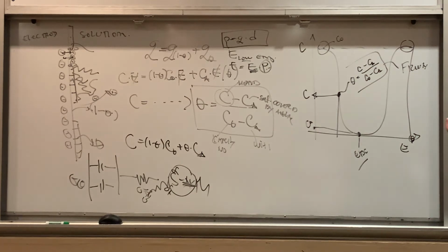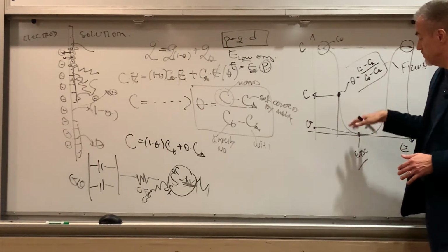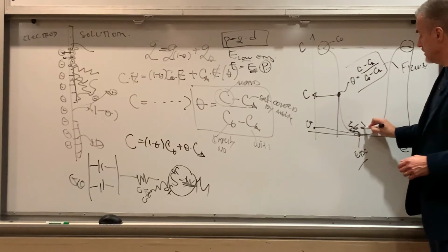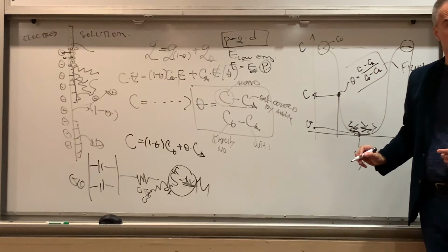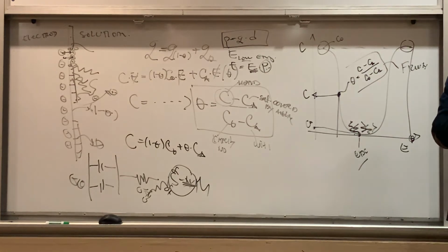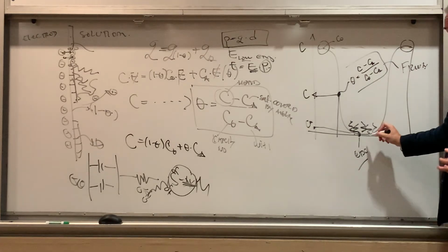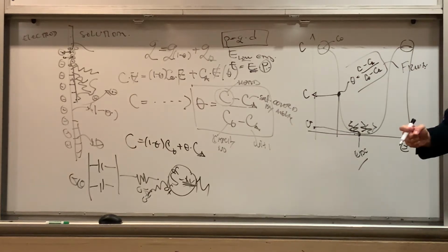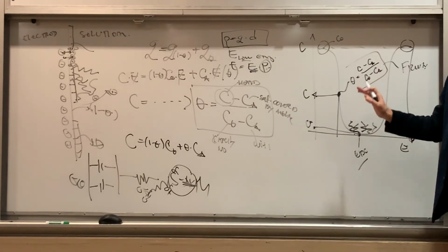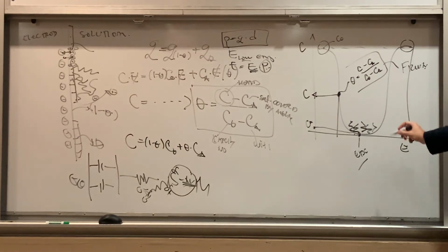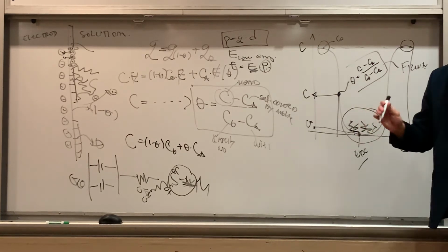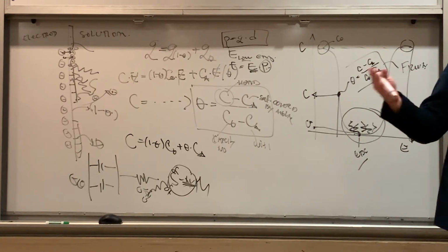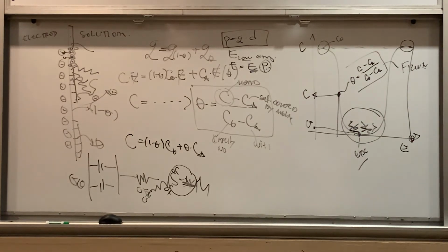Suddenly, the system can actually minimize its energy adsorbing big molecules, because the field is so weak that the net gain in terms of the stabilization due to the formation of the adsorption bond is much better than the electrostatic energy that is satisfied by this whole business of adsorption. And that's why organic additives that we use in electrodeposition always do adsorb around the PZC, potential of zero charge.